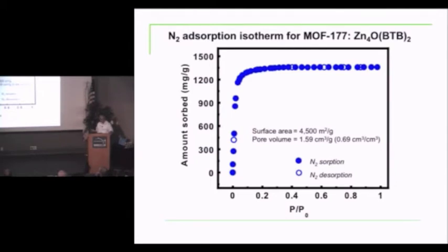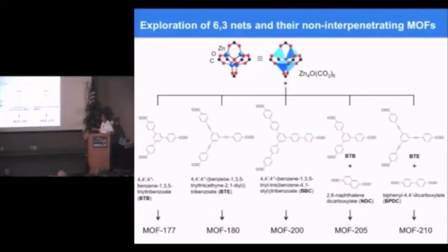Now we are able to evacuate the pores very efficiently and get even 6,000 square meters per gram. That's around 4 times the previous record held by porous carbon and by other porous materials, both crystalline and non-crystalline. In this case, MOFs are crystalline. They have well-defined structures, and as I showed you, the components of which can be varied. And so then the race began, after that report, on an international level to try to beat that record. And so in my own laboratory, we made some of these links and tested their porosity, predicting even higher